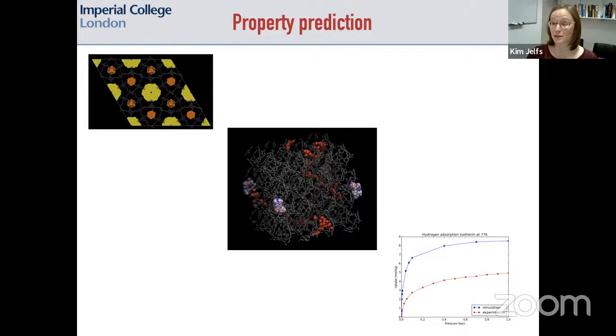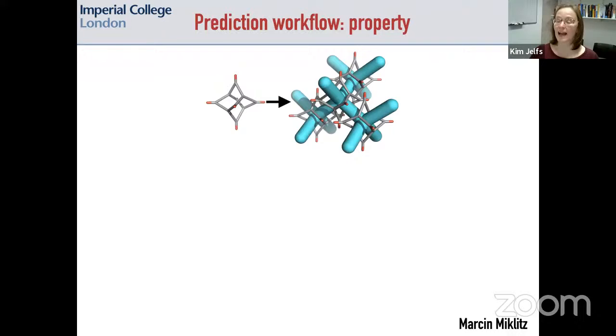So these are things you can do if you have a solid state porous structure. But given we had the aspiration to be predictive and look at hypothetical systems for these porous molecular systems, we won't have the solid state structure very easily to hand. As I explained, if we're screening thousands of systems, it's completely not practical for us to also predict their solid state crystal structure, because those simulations are too expensive. But at this point, what we thought to do was to take advantage of the fact that these systems are relatively unique within porous materials in that they are intrinsically modular and molecular. So here I've got a schematic trying to represent that. Here I've got the typical tetrahedral symmetry cage. It's got 4 different cavity windows shown on the left. And then on the right is a very typical packing mode that you see, where each of these windows line up.